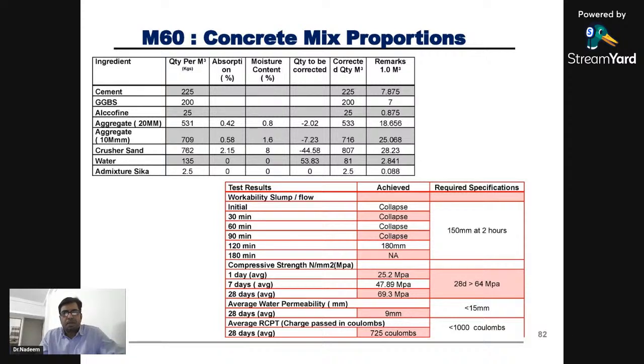These are the requirements of slump in the initial phase: up to 90 collapse, 120 minutes 180, and 150 mm at 2 hours. Strength, of course, these are the actual strengths. For M60 grade, the 28-day average achieved is more than 64 MPa. Then these are the RCPT values: less than 1000 was specified, and on average they got 725. With water permeability specified at less than 15, on average they got 9. So these are the specifications they were able to achieve.